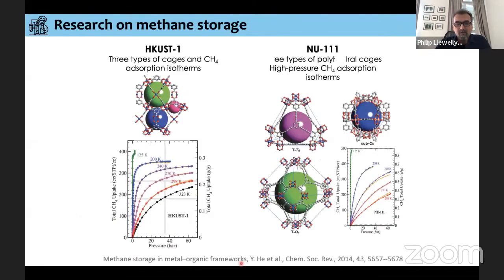So just to show you, from this review, two results with two different materials. So this is copper BTC, or HKUST-1, which has three different types of cages. And we can see here the methane isotherms at different temperatures. And on the right-hand side, we have the similar thing for a material known as NU-111. And again, we can see these isotherms, the uptake as a function of pressure. They're quite gradual isotherms, also known as Langmuir isotherms. And we can see that there are no specific features in these isotherms, as we've seen for hydrogen so far.